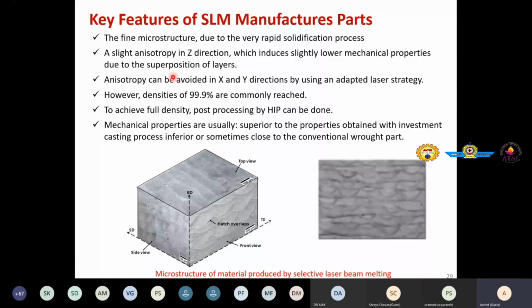Anisotropy in other directions like X and Y direction can be minimized using a good laser traverse path. In SLM parts, a typical density close to 99.9% can be easily reached, of course, with good choice of parameters. Sometimes, if density is not good, we adopt post-processing like hot isostatic pressing, HIP, where the porosity can be closed and density can be improved. The mechanical properties of SLM parts are usually superior to the property obtained with the investment casting process, but inferior or sometimes close to conventional wrought parts. So this is important information.